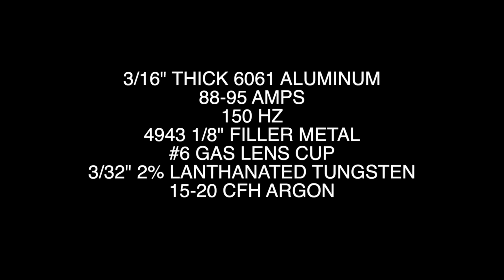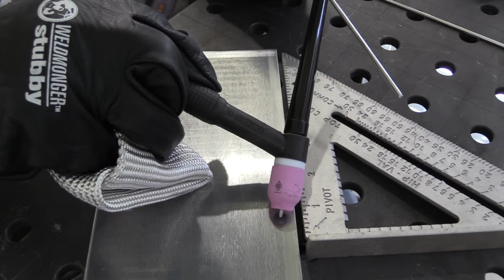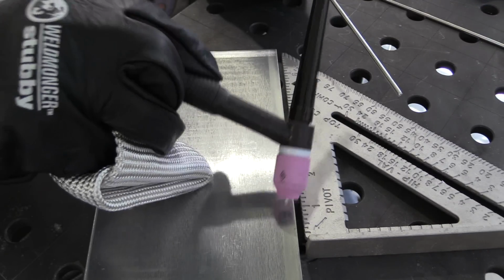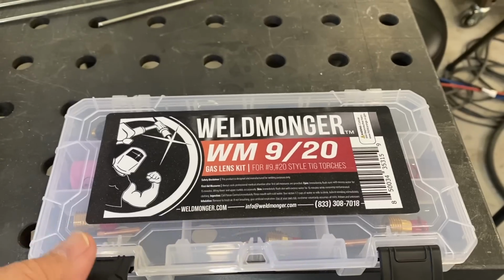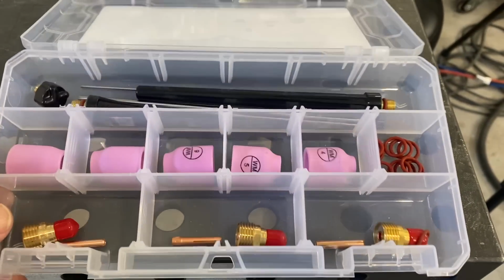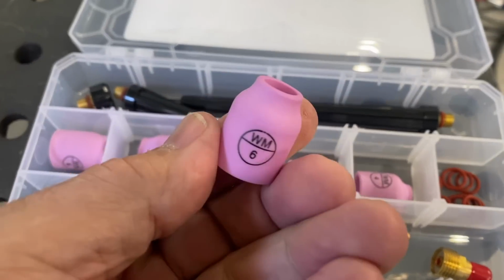Okay, here's the amperage and the settings and all the details that it took to run a bead right next to the edge on 3/16 thick 6061. That was a fairly normal, safe travel speed, but now let's see if we can increase that travel speed to almost double. I'm using a CK20 style water-cooled torch with a number 6 gas lens.